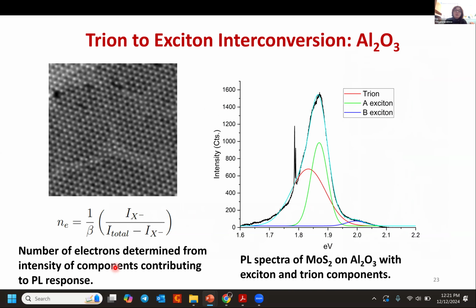then what did we do? We tried to examine a sample which was freshly grown on sapphire, provided by Penn State. Thank you, guys. And then we applied advanced fitting analysis, and we looked at how MoS2 on sapphire responds to laser irradiation. You can see here photoluminescence spectra of such a sample, which we fit with B exciton peak, A exciton peak, and trion. Of course, even from the beginning, the as-grown sample has a little bit of trion influence, which is fine.